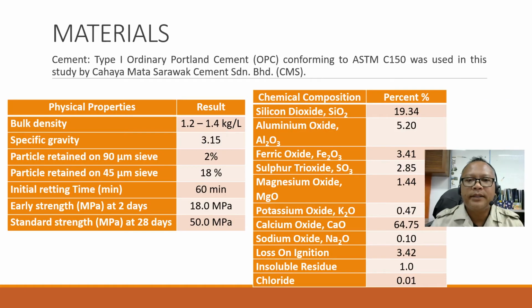The material used in this research, first is cement, type 1 ordinary Portland cement or OPC, conforming to ASTM C150 by Cahaya Mata Sarawak Cement Berhad. If you look at the table of physical properties for the cement, the bulk density is 1.2 to 1.4 kg per liter, specific gravity 3.15, particles retained on 90 micrometer sieve 2%, particles retained on 45 micrometer sieve 18%, initial setting time 60 minutes, early strength at 2 days 18 megapascal, standard strength at 28 days 50 megapascal.